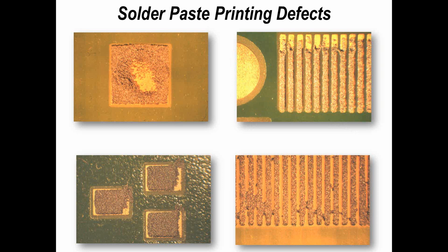On the bottom right-hand image, you can see a wet deposit, what I refer to as a wet short. So where you've got solder paste which is shorting between fine pitch, which may or may not cause a short during reflow. If you look at this example, probably the examples on the right-hand side where you can see a very minor wet short probably won't. But the one on the left-hand side of that particular image will cause a short.